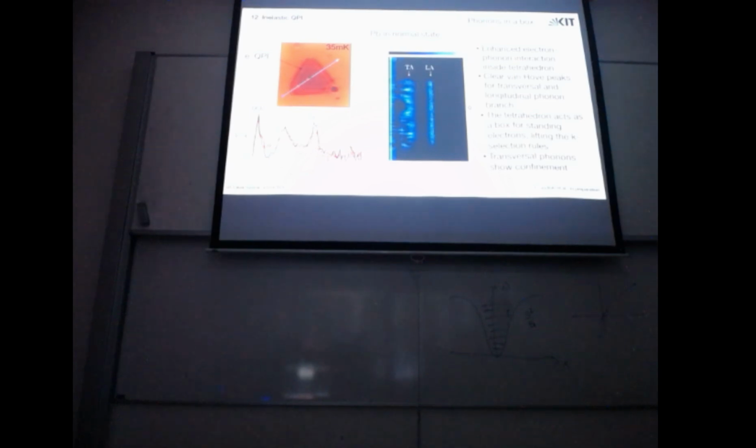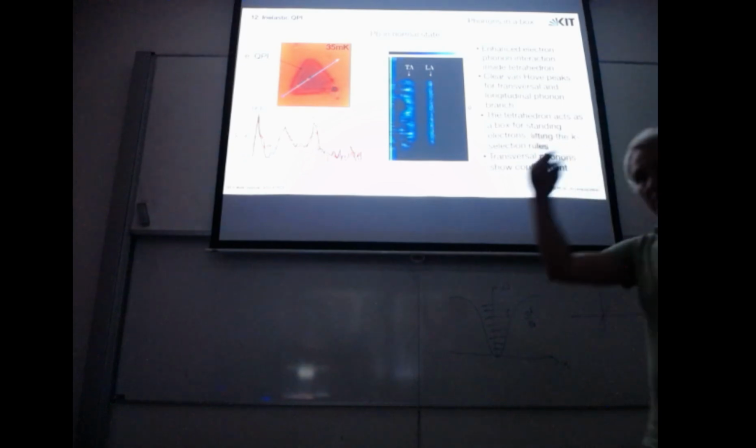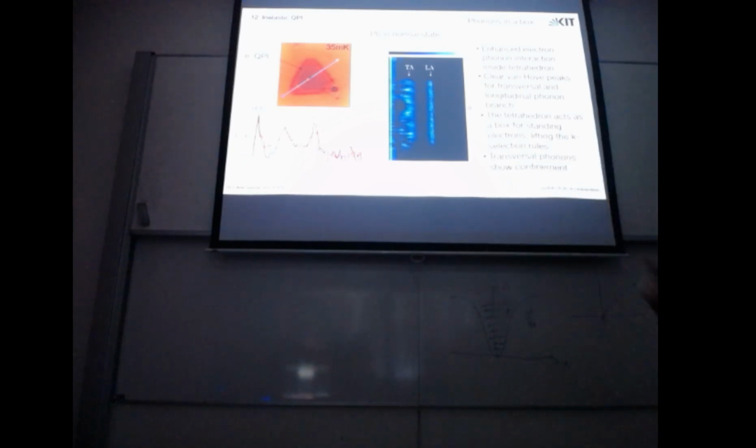So actually, when we have this inelastic scattering, we go from essentially the same electronic wave function to the same electronic wave function and excite a phonon. The difference is small in energy, and the width of the quantum well state is just larger than this energy difference of the phonons. That means we don't have this restriction of momentum conservation, or Q, anymore. These are all localized states, and we tunnel from one localized state to another localized state and excite the phonon.